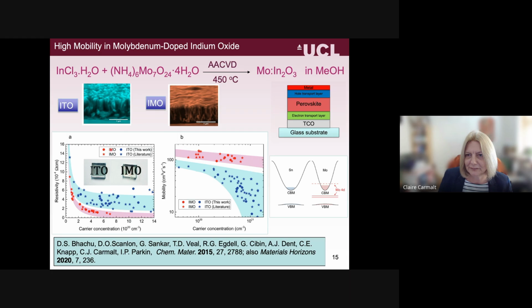I'm showing the IMO in red and ours are the circles, and the ITO in blue and ours are the circles, and we're comparing it to literature by the stars. So you can see for the IMO you get lower resistivities than for the ITO, so that's good, lower resistivity, so better conductivity. And also importantly, you actually get higher mobility as shown for IMO versus the ITO.